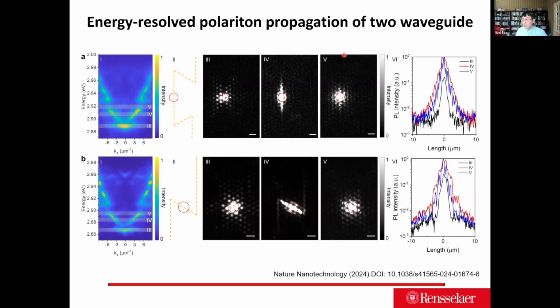Cesium lead chloride is super stable. Because think about it, they work in the region of about 430 nanometer, the polariton mode. And you have a DBR structure that's centered around 430 nanometer, which has a bandwidth. So that means you have to pump at about 350, 360, 370 nanometer, which means your femtosecond laser or CW laser has to go into the UV regime. So we have PMMA on top. The typical experiment we observe is that the PMMA is damaged first, but the process still works fine.